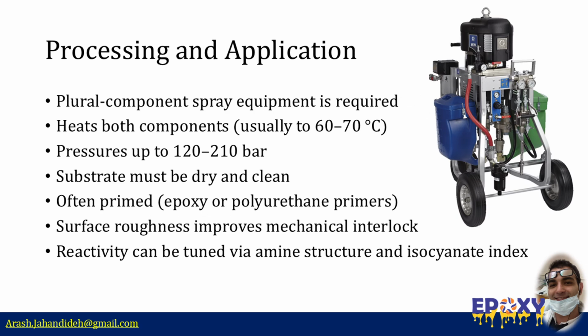Processing polyurea systems requires special equipment due to the speed and sensitivity of the reaction. Typically, plural component spray machines are used. These systems independently heat and pressurize the two components before mixing them at the spray gun nozzle. Both the isocyanate and amine components are usually heated to around 60 to 70 degrees centigrade and sprayed at pressures ranging from 120 to 210 bars to ensure proper atomization and mixing.